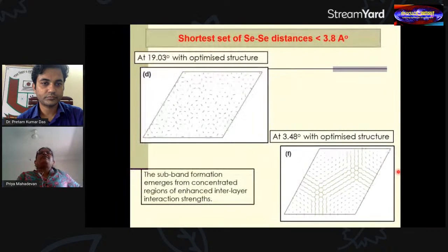Whereas when I had the other case, which was the large angle, it seems to be randomly distributed through the unit cell. And so these concentrated regions of large hopping interaction strengths lead to large perturbations in these regions, and lead to what we find here, the subband formation. The strong perturbations in these regions lead to the subband formation, and this is possible for these small angles, whereas it's not possible in the large angles. What I showed you in this picture is that you have these patches of different high symmetry stackings, which come about in your low rotation angle structures, which is not there for the large rotation angle structures.